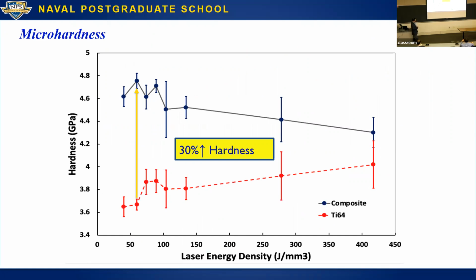You get a significant increase in hardness across the entire spectrum of energy densities. And keep in mind that that's despite having much higher porosity. So our strengthening mechanisms are making up for that porosity. And you'll also see that you get the largest strengthening effect here at about 60.